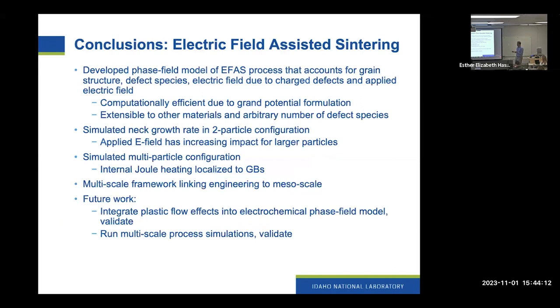So just to sum up the work there, I'll go through this quickly so I have a little time to talk about my last topic. Basically we've developed a model of electric field assisted sintering that accounts for the grain structure, the defect species, and the electric field. We've applied that, as I said, we've done some work on neck growth, which I didn't quite have time to go into, but also looked at multi-particle configurations and saw that the heating is localized to the grain boundaries. Eventually, we're also working on incorporating plastic flow effects. So we have a collaboration with Professor Edwin Garcia from Purdue, and he's been working with us on the plastic flow effects. And in the next year we're working on merging those two models and also strengthening the connection with the engineering scale model.